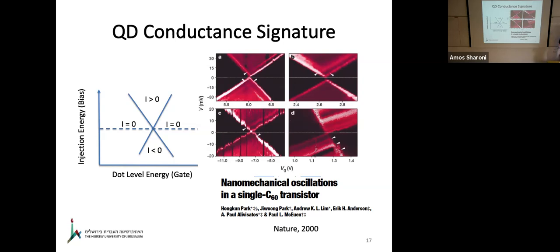But if it's a good metal, even if they're turned around, the picture is breaking down now because you don't have these very clean energy levels, because you have some junk coming there and disturbing it. I mean, it's so unstable that whether it's stable or not depends on its environment. Most of these measurements are done at very, very low temperatures, so things tend to go more stable because a lot of these fluctuations are quenched. But then each dot will be different, because each dot will have some quenched environment or whatever.